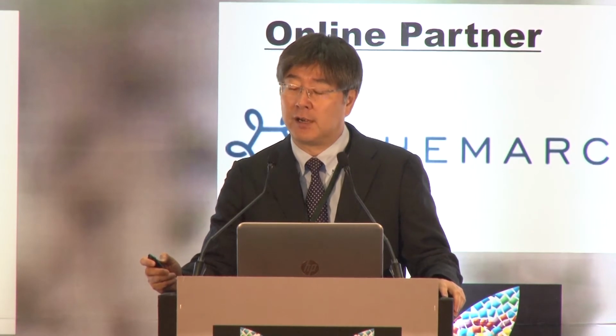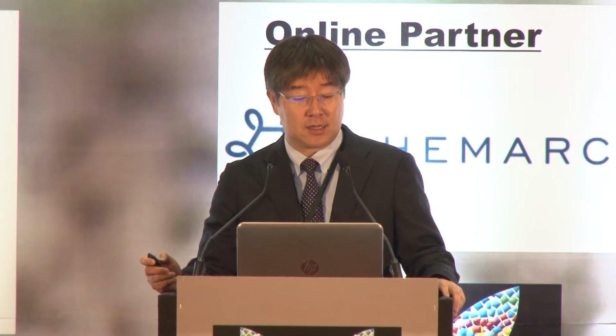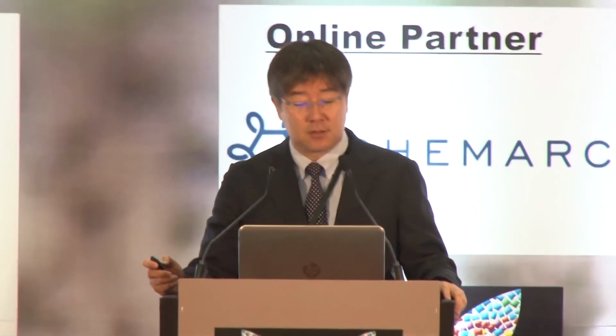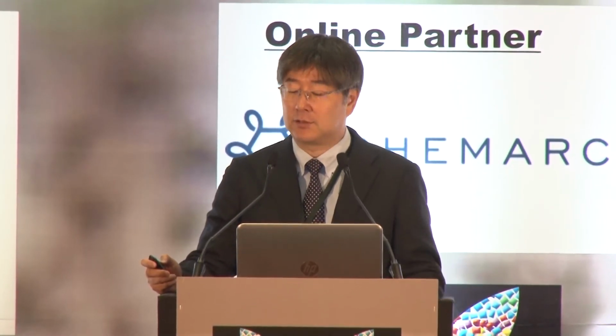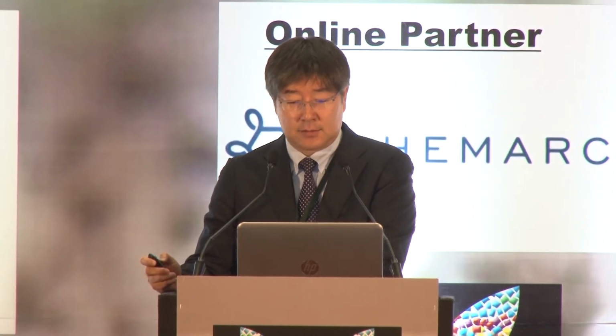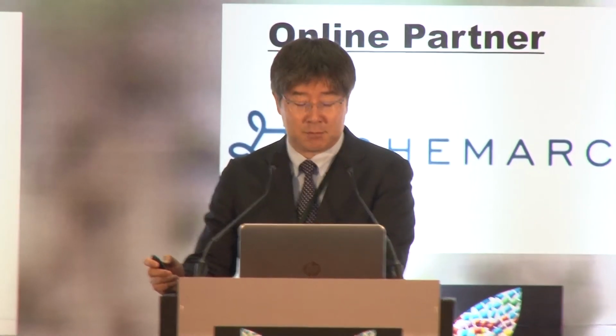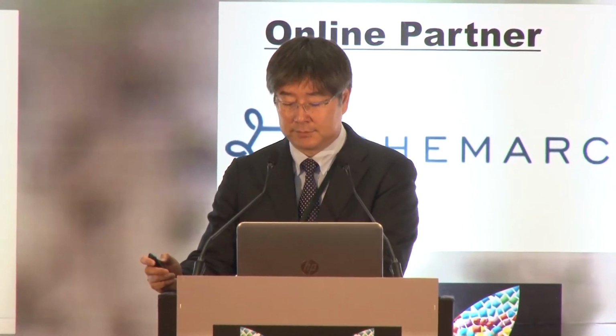So it means N-methyl HALS have higher activity to trap free radicals or unstable intermediates, resulting in inhibition of the chain propagation reaction in oxidation. So in terms of the thermal stability, N-methyl HALS is very good.